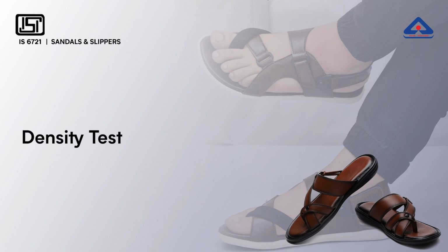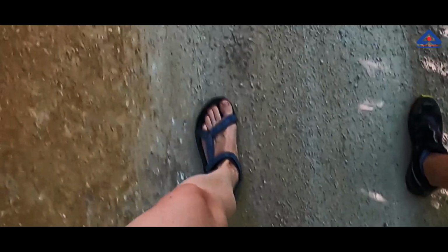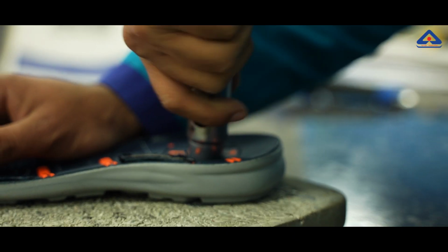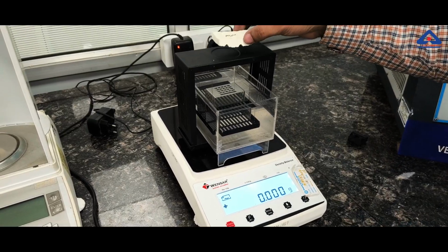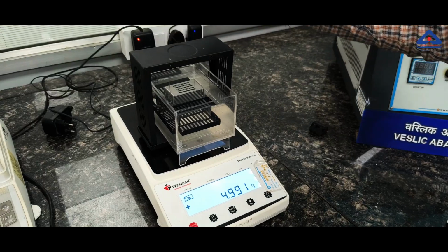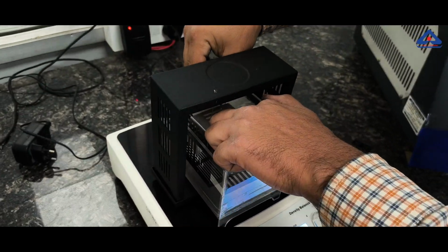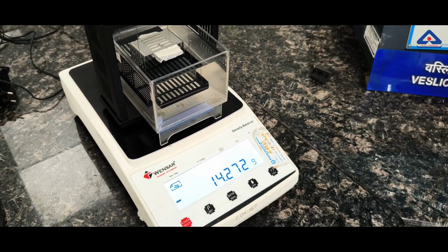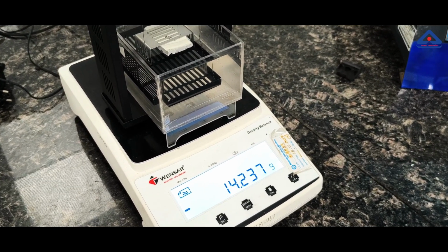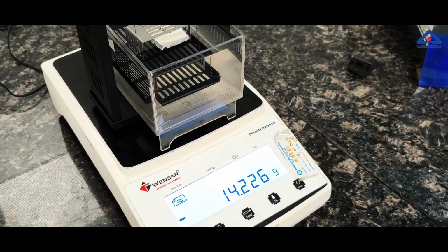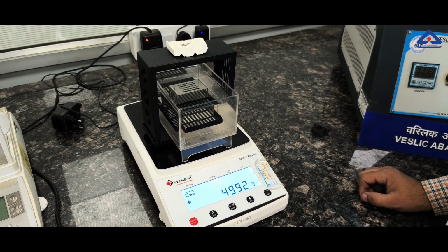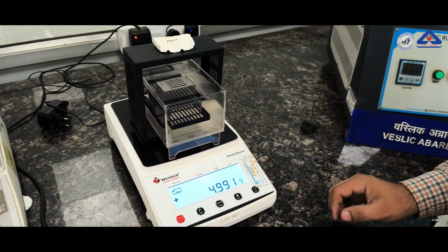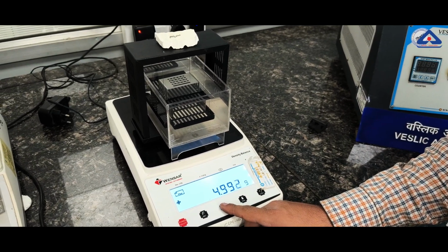Next, we perform the density balance test on the sandal sole material. In everyday use, the sole's weight and composition affect comfort and durability. For this test, a sample is carefully cut from the sole and weighed in air using a precision balance. Then, it's submerged in water and its weight is measured again. By comparing these two weights, we calculate the material's density. This ensures the sole meets the required standards for quality and performance, providing the right balance of lightness and strength.